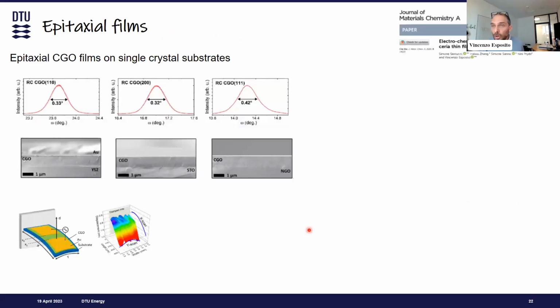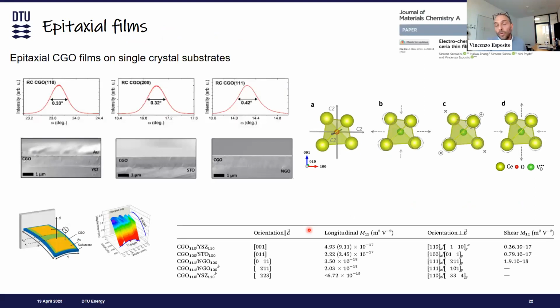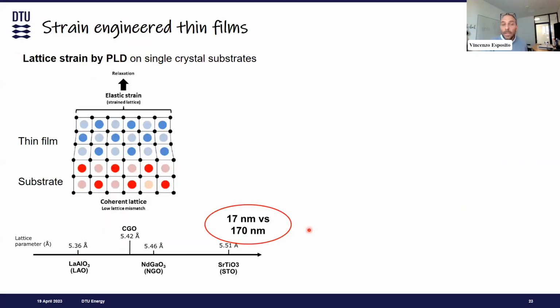The other possibility is actually to change the orientation of the substrate and get a fully relaxed system, and now explore what is the best possible orientation for the electrostriction effect in CGO. For example, in this study, we discovered that the 0-1 orientation is slightly beneficial for the electrostriction effect in these materials. But going back to the strain, of course, we can make a direct comparison between what happens in completely strained films and in relaxed films. And this can be done pretty easily, just by tuning the thickness of the film. So when we make thin films that are below 10 nanometers, there is a pretty high strain coming from the substrate.